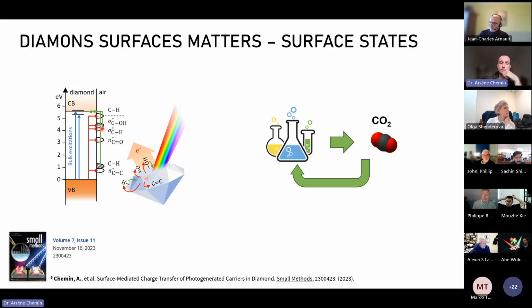And that is particularly interesting because those surface states can actually be photoexcited within the visible light. So even though the diamond bandgap is very wide, 5.5 eV, those photoexcitation happens, and we can use that to do some chemistry and, for instance, use diamond electrodes to reduce CO2.